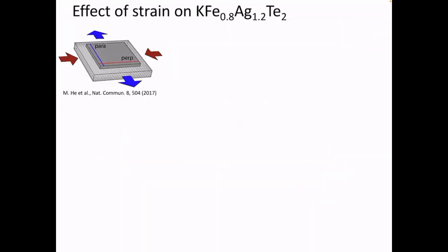All right, and then we'll try to probe this material with strain, which is a very natural idea given the similarities shown in the previous slides. The method that we take is this approach first pioneered by Christophe Meingast's group, which is to glue a sample onto a substrate that has a differential thermal contraction when you cool it down. That's because you have some glass fibers in this plastic substrate, which gives a differential thermal contraction upon cooling.